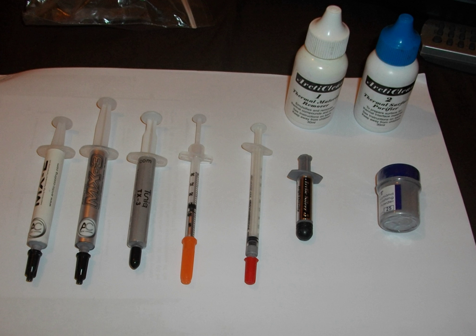The filler loading can be as high as 70–80% by mass, and raises the thermal conductivity of the base matrix from 0.17–0.3 W/(m·K) up to about 2 W/(m·K). Silver thermal compounds may have a conductivity of 3 to 8 W/(m·K) or more, and consist of micronized silver particles suspended in a silicone or ceramic medium.